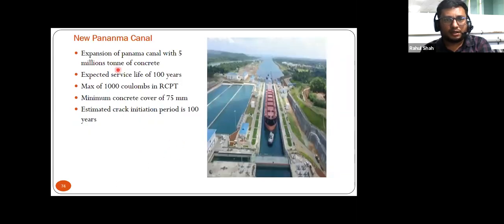New Panama Canal. They have an expansion of the Panama Canal with 5 million tons of concrete. They have an expected service life of 100 years, and a maximum of 1000 coulombs in RCPT value is set, right? And they have a minimum concrete cover of 75. And initially, this is very much important, the estimated crack initiation period is 100 years. So this is nothing but the service life equation they have used, so that they have taken care of all the parameters which can initiate.